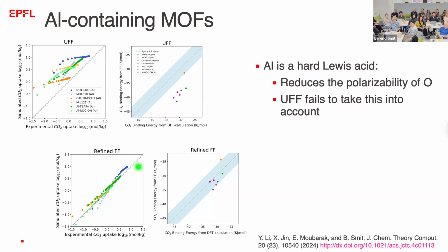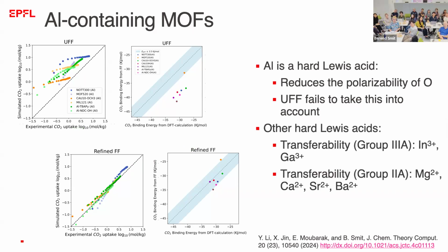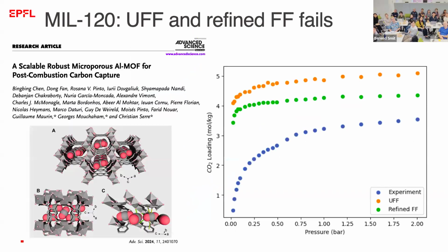He really was very, very successful because after his tuning, he really got it right. So that was interesting. But he really got annoyed with this MOF. So this is an aluminium MOF. It's done in the Paris group. So here are the experimental data. This was the original UFF, and this was his model, and it's still very far from the experimental data. And that was one of the MOFs that really, really failed.